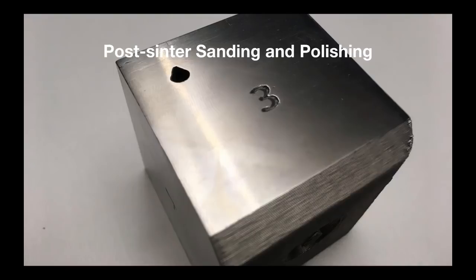And actually, on that point, we did get a couple of questions about that as far as what are the metal characteristics post-sinter? So they're generally what we consider an as-sintered state. Oftentimes, for instance, with 17-4, it's pretty close to a solution annealed state. It's certainly not hardened out of the sintering oven. You can pretty much perform any sort of heat treating, post-sinter hardening, what have you, on any of these metals, as long as you can do it on the underlying metal. So for 17-4, you can precipitation harden it beyond what you get out of the furnace.